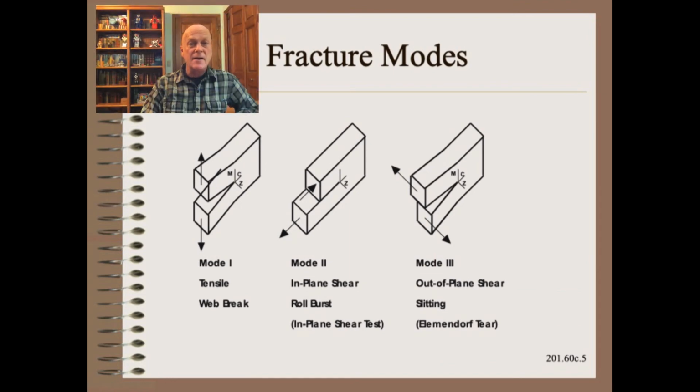Brittle web breaks are dominated by fracture. The tensile fracture mode 1 is what the web experiences most of the time in your machine. In contrast, most lab tests, such as the Elmendorf tear, measure mode 3. As a consequence, fracture provides us a super useful concept, but perhaps not so much a predictive utility. In the next slide, we will show why fracture helps us understand key attributes of web breaks.